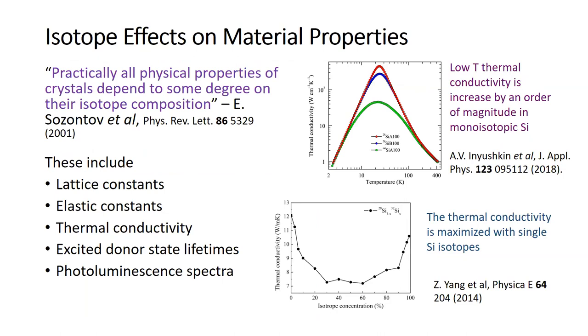I have this quote that practically all physical properties are dependent to some degree on their isotope concentration, including lattice constants, elastic constants, and especially things that involve the motion of phonons. So thermal conductivity is something that really varies. If you look at the top left, an example from silicon: natural silicon has three isotopes, but if you only have one silicon isotope, then the thermal conductivity at low temperature increases by an order of magnitude.